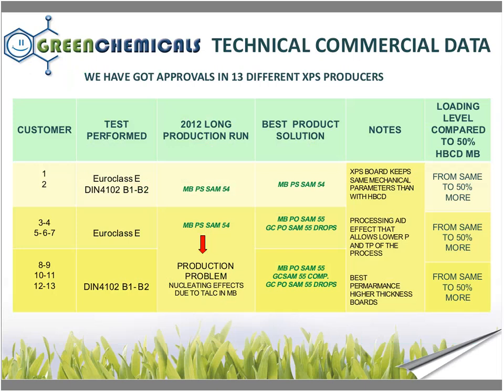Now we come to the commercial aspect. We got approval from 13 different XPS producers, mainly in Europe, which prefer not to be named in order not to disclose know-how. The tests we had to pass were Euroclass E or B1 and B2. We started sampling MBPS SAM 54, and as I told you before, only 2 could go ahead working with this product because the others got nucleating problems during production. So most of them moved to MB PO SAM 55, the one with the LDPE and EVA carrier, and some to drops and the compacted version. The XPS board keeps the same mechanical characteristics as a board with HBCD.